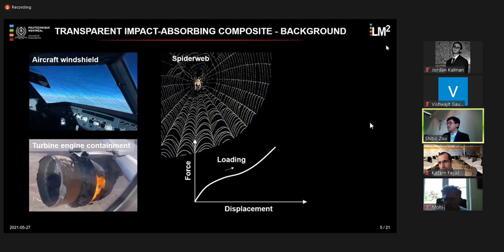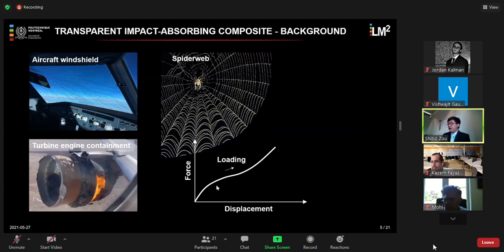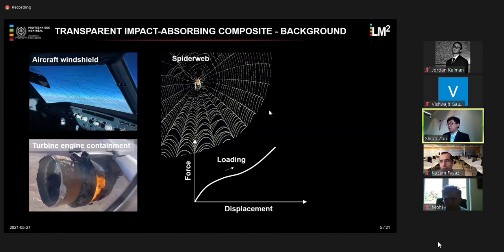As you can see here, the force-displacement curve of a single silk thread. The area under this loading curve represents the total amount of energy absorbed by the spider silk. And upon unloading, the area under this unloading curve represents the elastic energy that will be released upon unloading. And in between this loading and unloading curve, this is the actual amount of energy that has been dissipated out